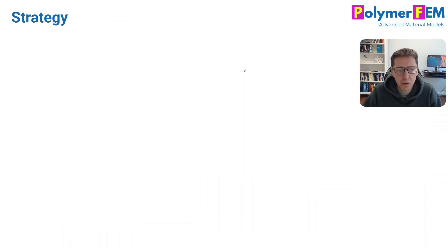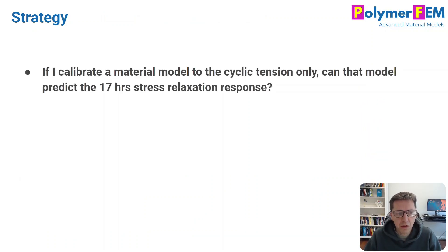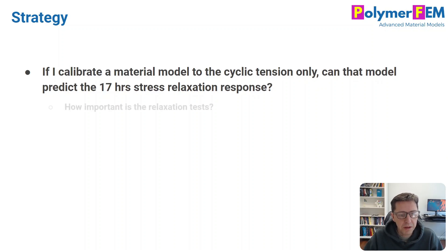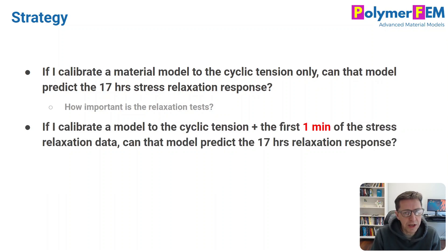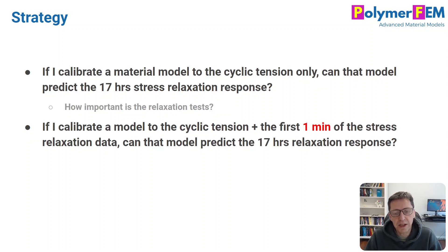The idea is to explore different things. What happens if I calibrate a material model to the cyclic tension data only? Will I be able to predict the relaxation data up to 17 hours? In other words, how important is the stress relaxation experiment by itself? Another test I can explore is: what if I calibrate the model to the cyclic tension data plus just the first minute of the stress relaxation data — truncating and ignoring the last part — and then see if I can predict the response up to 17 hours?